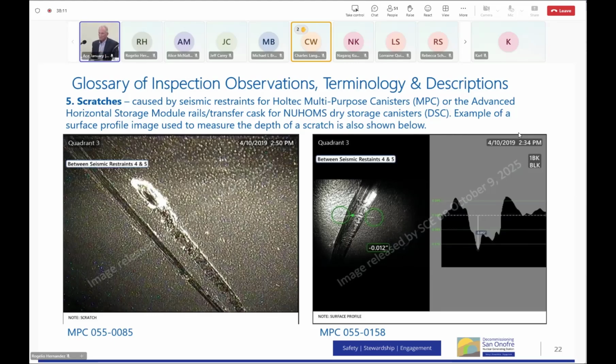On the right, we're doing a surface profile of a scratch. I talked earlier about how the robot can measure to 1/1000th of an inch. Well, that's what's happening there on the right. It's measuring the depth of the scratch to 1/1000th of an inch. Okay? And that scratch is 12/1000ths of an inch deep. You can read that on this slide. And there's the surface profile generated across that scratch on the right.